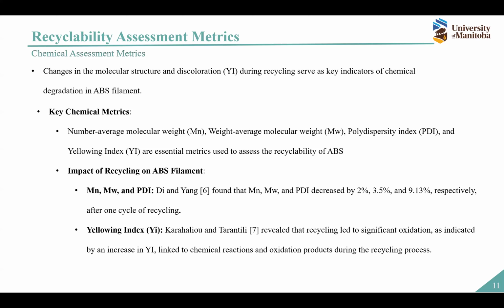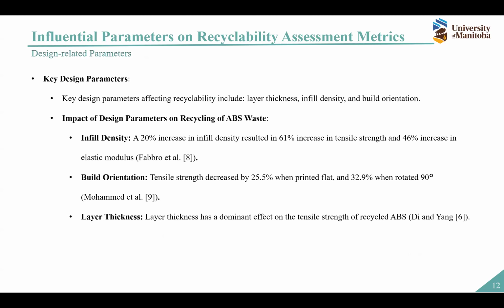Different researchers also investigate recycling based on measuring the chemical metrics. For example, Di and Yang found that the number average molecular weight, weight average molecular weight, and polydispersity reduced after one cycle of recycling. Also, the yellowing index shows an increase after one recycling process, which shows actual chemical reactions and oxidation during the mechanical recycling process.